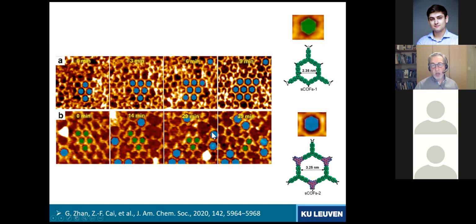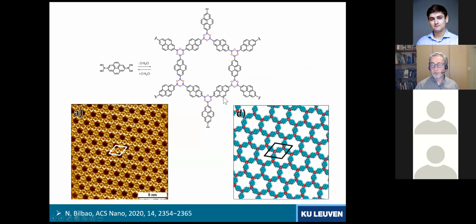We think that a lot is still to be learned from this when we look into the quantitative aspects, but at least so far, as a proof of concept, we have established that it is possible to follow this kind of reaction. We are also looking at different types of 2D covalent organic frameworks, such as the one shown over here. And just to remind you that all of this is recorded with scanning tunneling microscopy at the liquid-solid interface, at room temperature. And despite all of that, we can achieve pretty nice resolution.